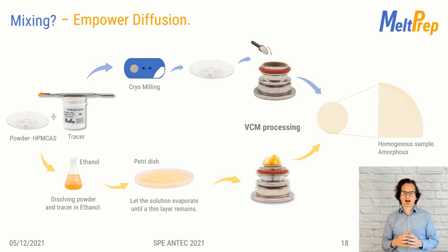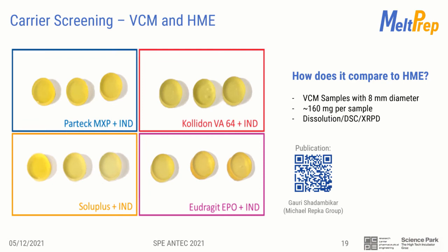Considering the mixing, I can also answer one of the most frequent questions that I receive in the pharma arena. Are VCM samples comparable to hot melt extrusion? Hot melt extrusion is the term used in pharma for compounding. Professor Repka's PhD student Gauri conducted a very comprehensive study. In this case, the model API indomethacin was used to study if hot melt extrusion and VCM yielded similar results. This slide shows images of VCM samples with 8 mm in diameter with some common carrier materials including Parteck MXP. The samples went through intensive characterization showing comparable data to hot melt extrusion.